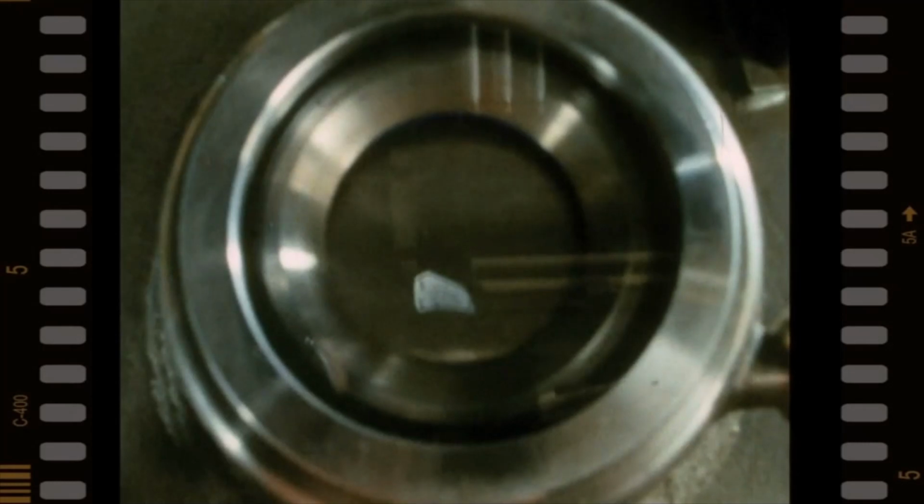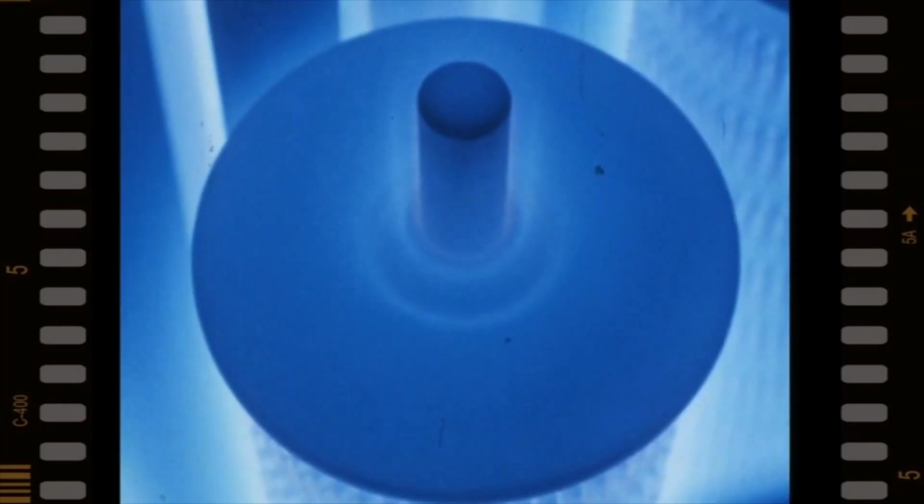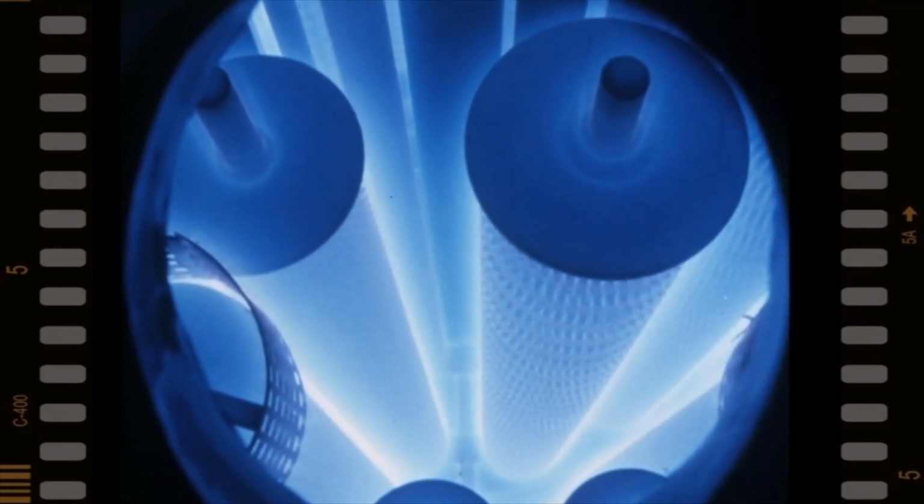The low-pressure furnace atmosphere is a mixture of 25% nitrogen and 75% hydrogen, and with a voltage of between 300 and 1000, the gases become ionized. The gear wheels absorb the nitrogen to form a hard surface layer. This is one of the many examples of high tech in the world of Ford tractor manufacture.